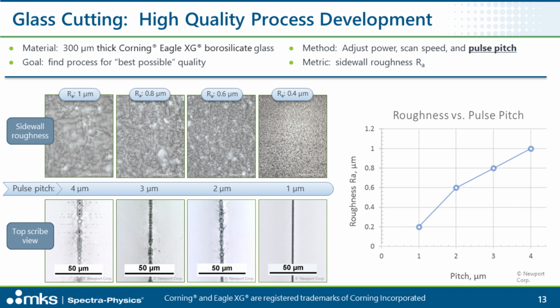And then the bottom pictures show the top view where we see the quality going from irregular ablation dots down to a very fine scribe line. If you look at the 1 micron pitch, you can see a very nice jump in the quality of the cut that was achieved. And graphically, measuring the roughness, this is shown on the right-hand side of the slide. We have the pitch on the horizontal axis, and from 4 to 3 and 2 microns, you have a linear improvement in quality, which is basically the reduction in the Ra roughness measurement. And then when you go from 2 to 1 microns, we have a jump, basically a doubling of the improvement that we see going from 4 to 2 microns.